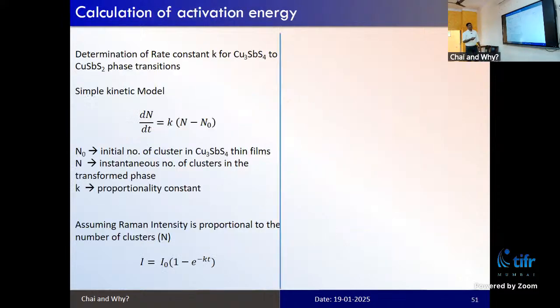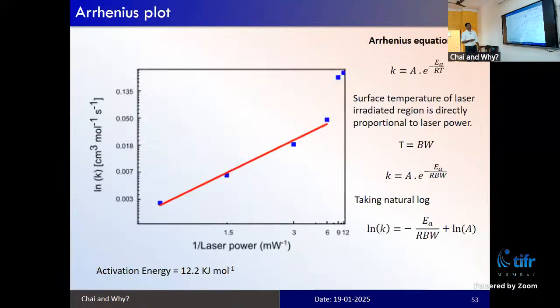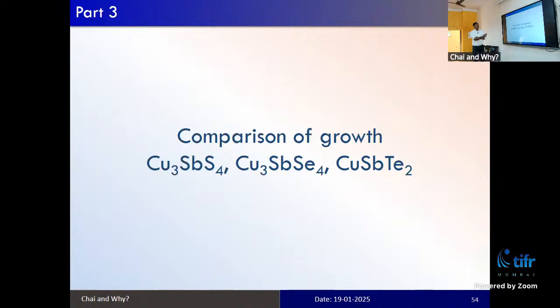So with this, we have calculated how much energy is required. The activation energy for transforming this material from Cu3SbS4 to CuSbS2 is something around 12.2 kilojoule of energy. So similarly, we have done copper antimony sulfide. We have also done copper antimony selenide and copper antimony telluride material systems.